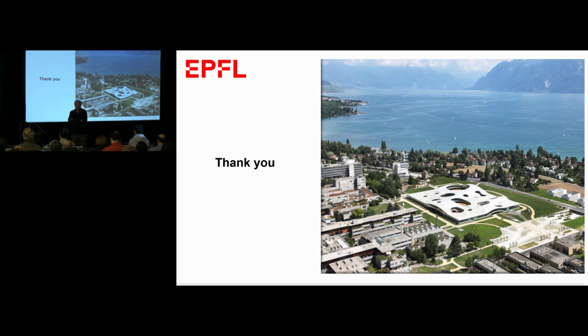The extrapolated lifetimes are now good, but these are accelerated tests, so are they giving the whole truth for outdoor? We also have to do outdoor testing, and that's going on. And with the day and night cycle, you certainly have to do temperature cycling. It's very critical for perovskites. But also there, no red flag has come up so far. So the progress has been enormous on the stability front. The only problem that is left is the lead problem. So we have to put those cells in a solar farm, maybe on the roof, and have some of them fenced in, because for consumer electronics, they wouldn't be a good choice, in my opinion.